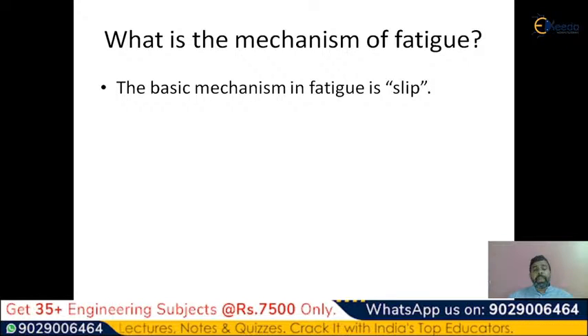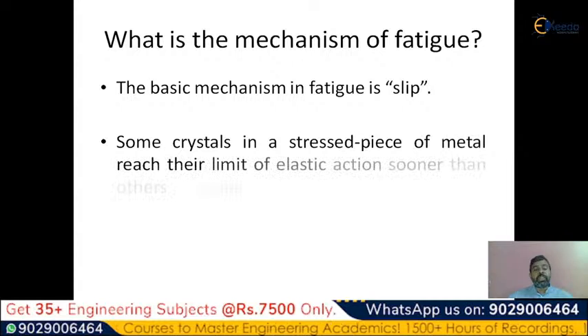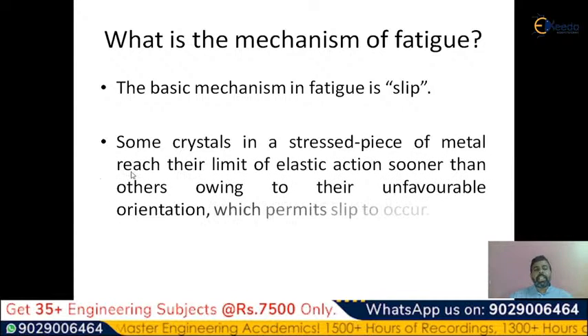In general, the basic mechanism in fatigue is slip. That means the background of the mechanism. Why does fatigue happen? Why is this failure observed in the material? Because of the slip. If slip bands are observed in the material, automatically we can say that some deformation exists. Whatever crystals you have taken in a stressed piece, that means load is applied on the material.